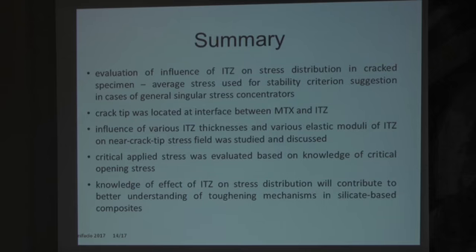In the summary, we evaluated the influence of the ITZ on stress distribution in the cracked specimen. The crack tip was located at the interface between matrix and ITZ. We evaluated the influence of various ITZ thicknesses and various elastic moduli of the ITZ on the near-crack-tip stress field, and also the critical applied stress was evaluated.